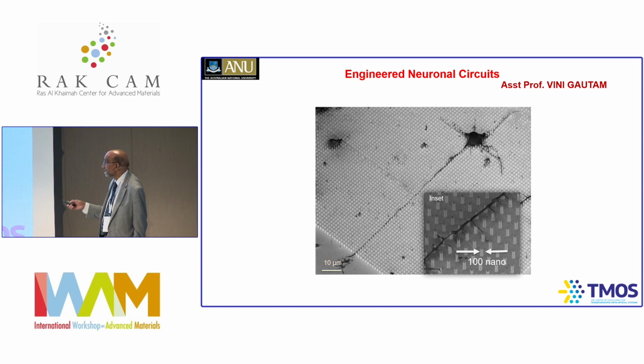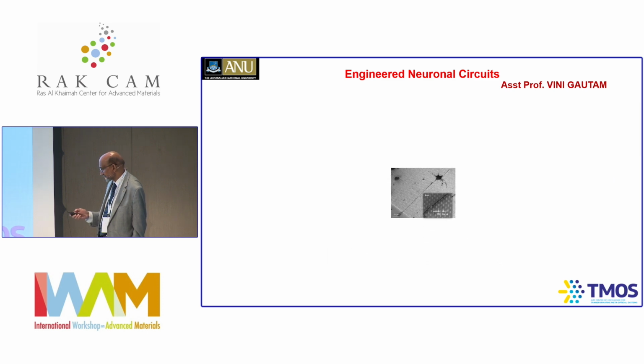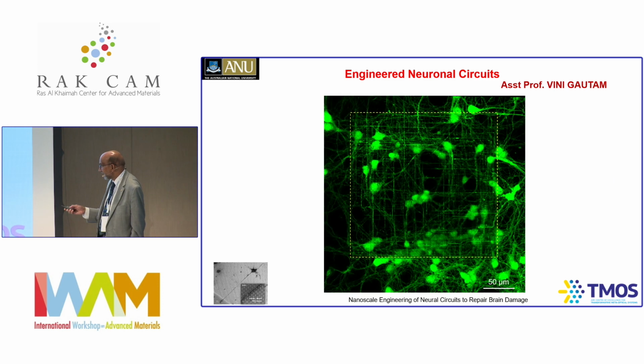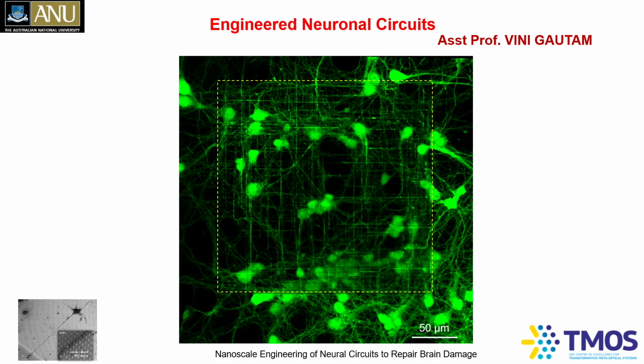You can order patterns here. It turns out when you grow this neuronal cell, which has a cell body, the soma, these neurites really follow these nanowire patterns beautifully. You can see the dendrites are also following these patterns very nicely. If you put more than one neuronal cell, they really form into a nice neuronal network. See, they're following these patterns very nicely. These axons and others really follow these patterns very nicely. These boxes are where the nanowires are. But on the indium phosphide planar surface, these neurites make random connections. They don't follow any particular pattern or anything of that sort.